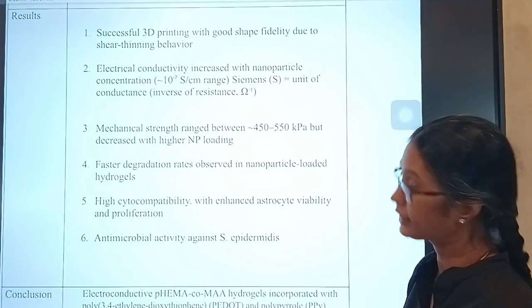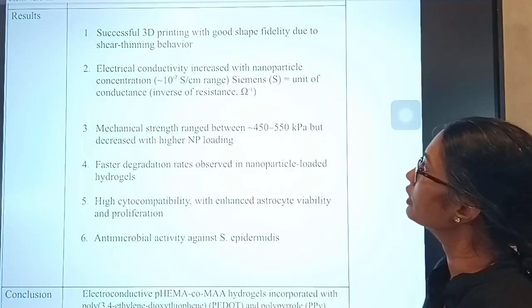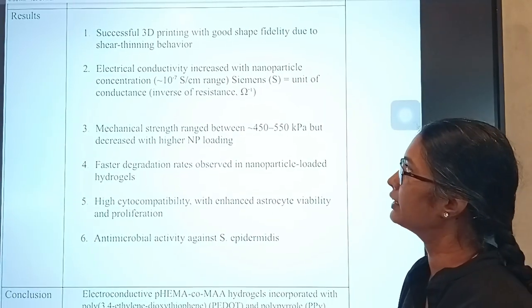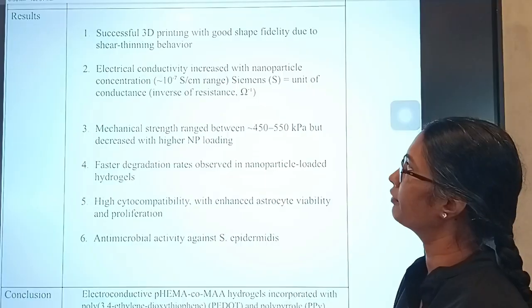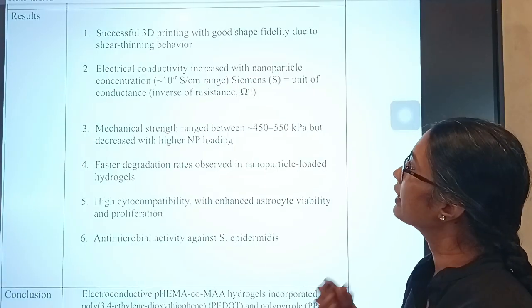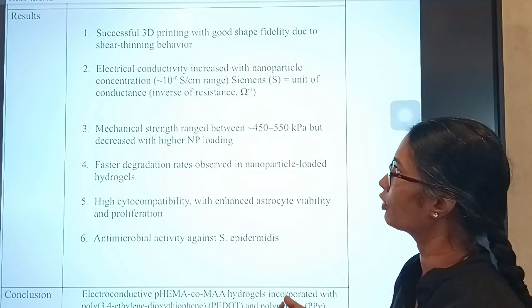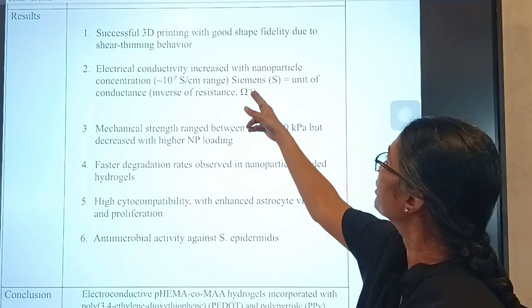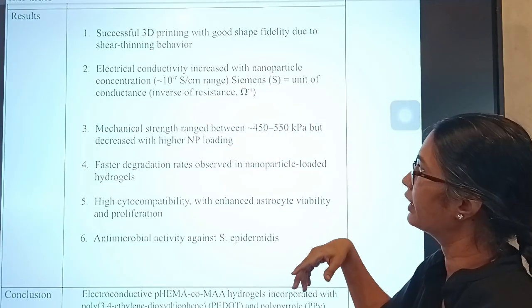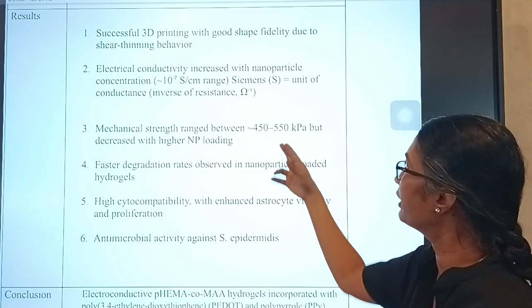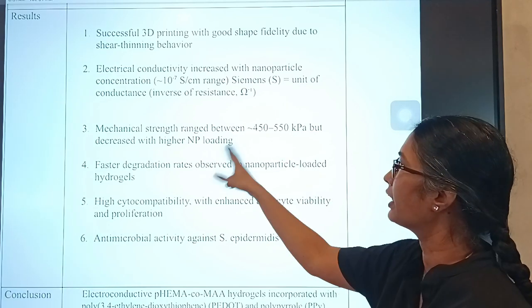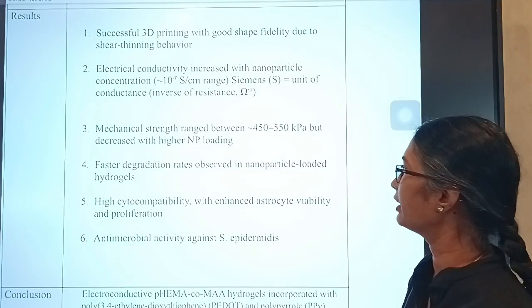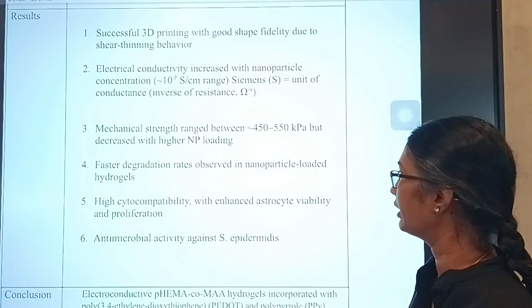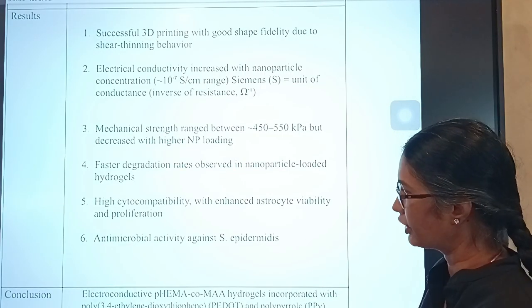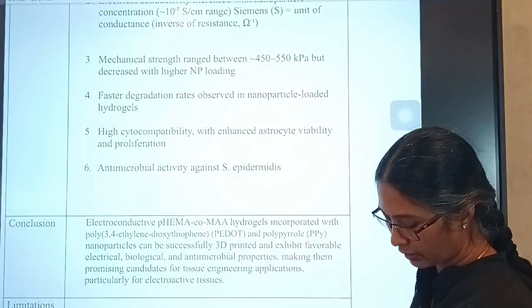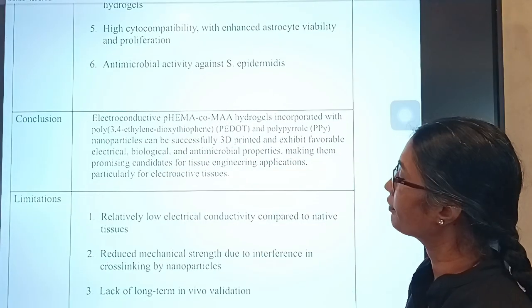So here they found successful 3D printing with good shape due to the shear thinning behavior, which means that while pressing it, it will flow easily. Electrical conductivity increased with the nanoparticle concentration, measured in S per centimeter, where Siemens is the unit of conductance. The mechanical strength ranged between 450 to 550 kPa, but decreased with higher nanoparticle loading. Faster degradation rates were observed, along with high cytocompatibility with enhanced astrocyte viability and proliferation. Antimicrobial activity was also seen against Staphylococcus epidermidis.